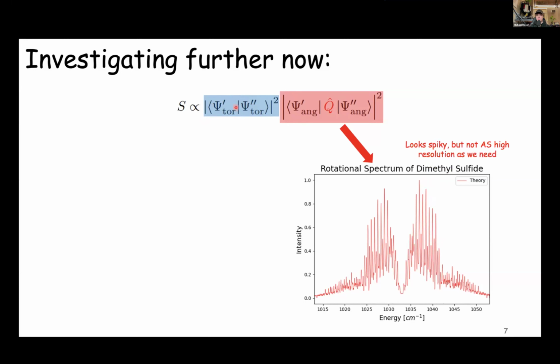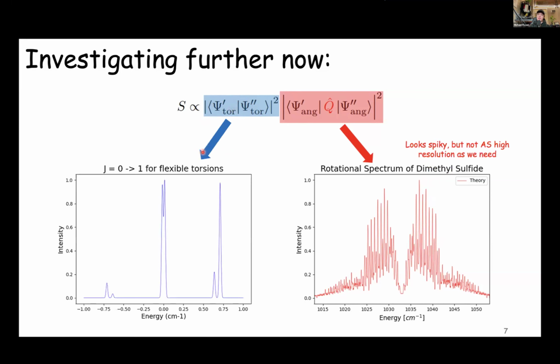So that's where this term on the left side comes into play. And if we evaluate this for just one of the peaks on this side, in this case, the J equals 0 to 1 transition for our rotor, we will see 3 sets of peaks where we typically would only expect to see 2 peaks. And we can map out what's occurring here. So for these peaks at plus and minus 0.75 wave numbers, we see that they have shifted around just a touch, and they have also split apart with a second peak picking up some intensity.